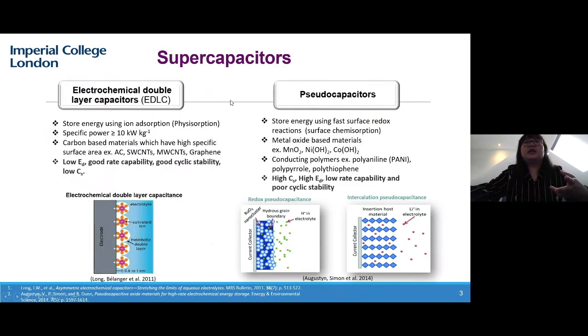They have two types, mainly divided by the mechanism that stores the charge. The first type, called electrical double layer capacitors, stores the charge via physisorption. So the material for the electrochemical double layer capacitor has to have a high specific surface area and also good conductivity to induce the ions to store on the electrode surface. In this case, the materials that are mostly used are carbon materials, such as activated carbon, single-wall carbon nanotubes, or graphene. However, the theoretical capacitance of carbon material is still low compared with pseudo-capacitive materials that use redox reactions to store the charge.